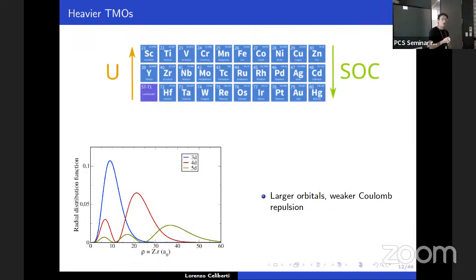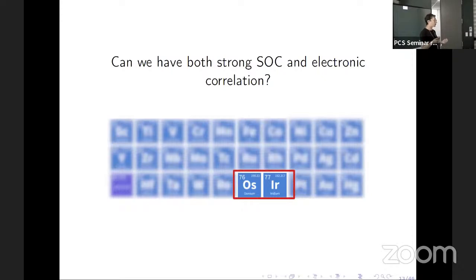And this can be understood by looking at the orbitals of the electrons. For 3D electrons, the wave function is much more localized, so the probability that the electrons are close to each other is much higher. So they repel much more. Whereas as we go down, the wave function is more delocalized, so the probability that the electrons come close to each other is much smaller. On the other hand, as we saw at the beginning, spin-orbit coupling increases as we go down the periodic table. So now the question is, can we find materials where both effects are strong? The answer is yes. And this happens especially in some osmium and iridium oxides.